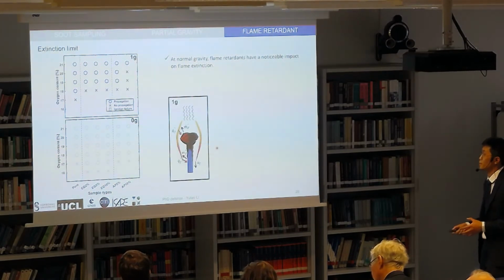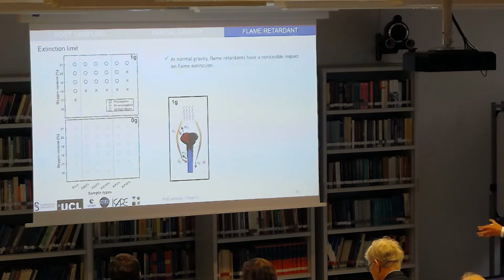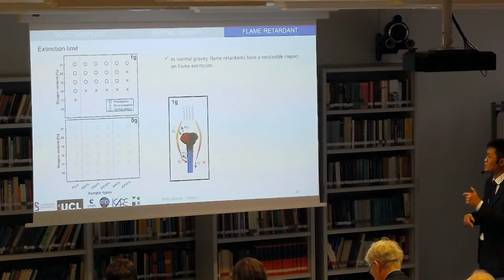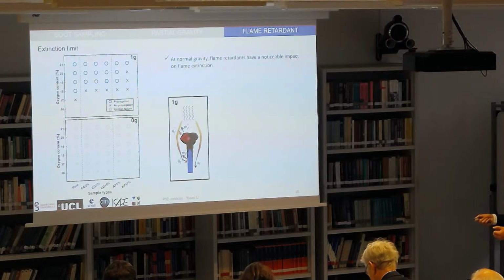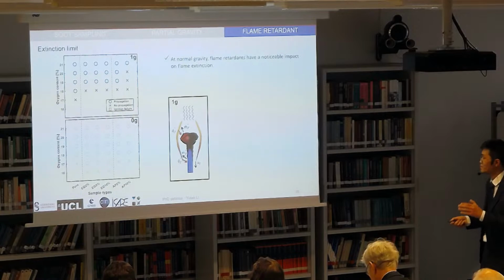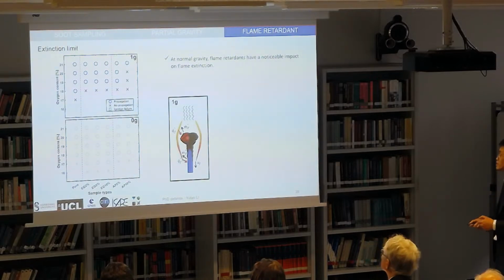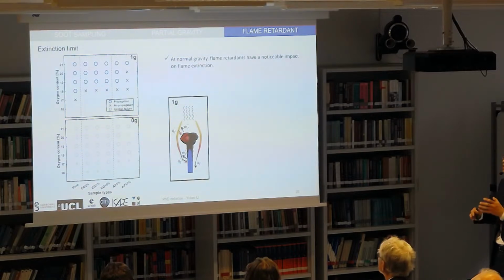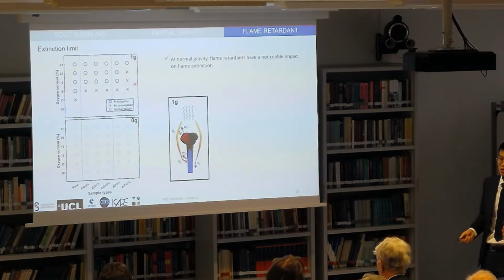A schematic here of the flame retardant may further explain the mechanism behind. At the leading edge of the flame, the addition of the flame retardant can slow down the local pyrolysis rate of the solid fuel, which can influence the overall pyrolysis rate and also the flame spread rate. And the intumescent downstream can block a part of the heat from the flame, which weakens the pyrolysis process and also contributes to the mitigation of the flame spread. When this performance is high enough, it can even stop the propagation. Moreover, the AP flame retardant provides a higher performance because the structure of the EG residues is not strong enough.